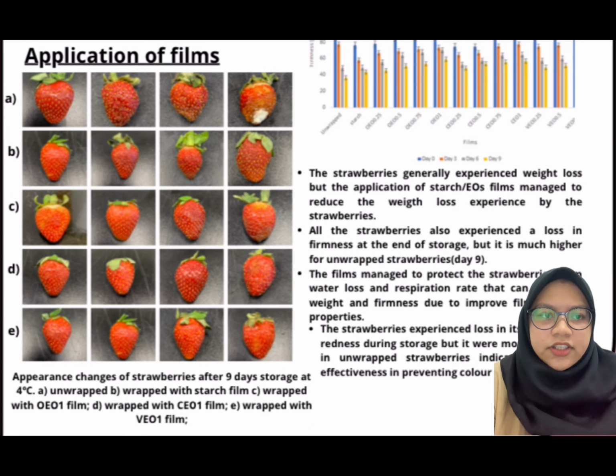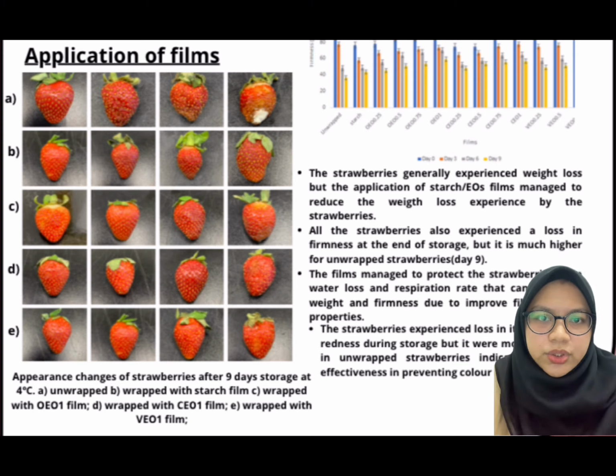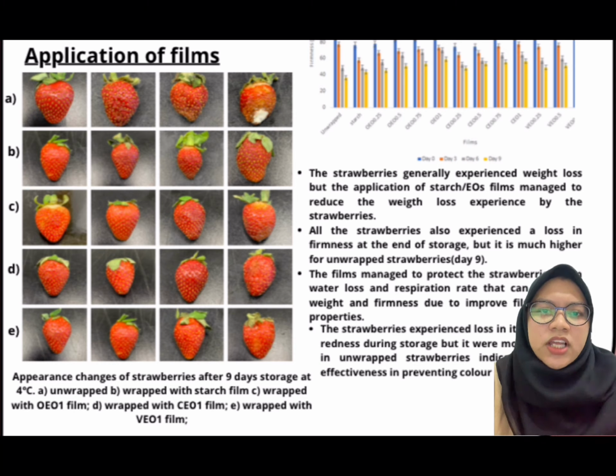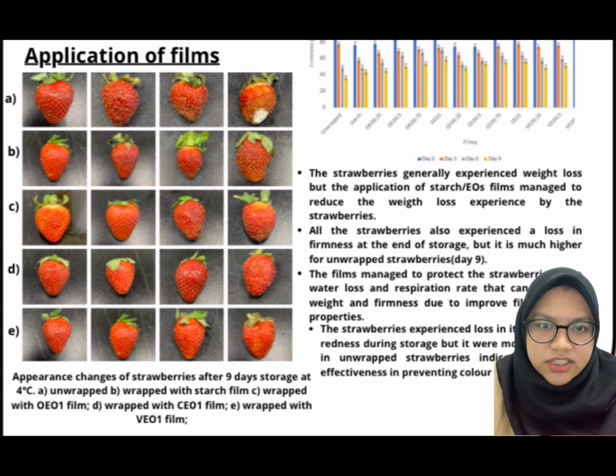Based on the figure here, the strawberries experienced loss in lightness and redness during the storage, but it was more pronounced in unwrapped strawberries, indicating that the films can efficiently prevent color deterioration of the strawberries.